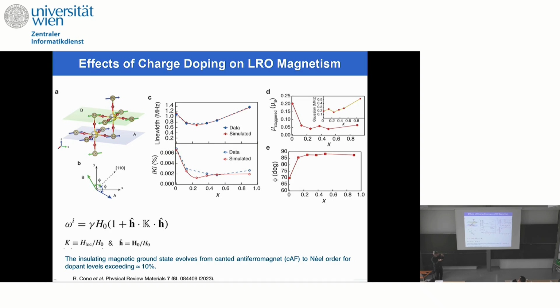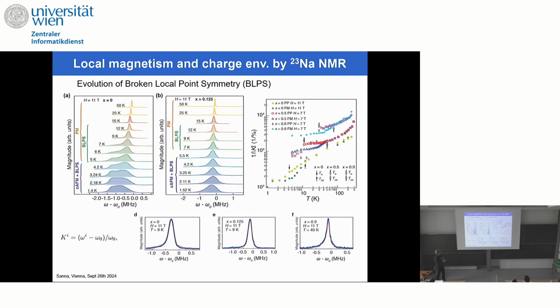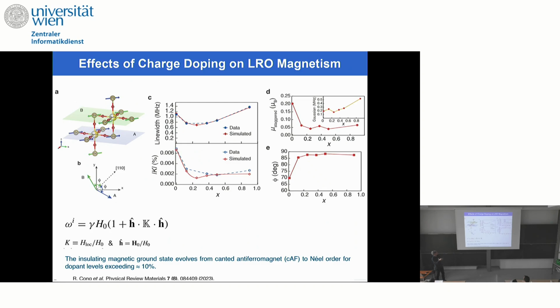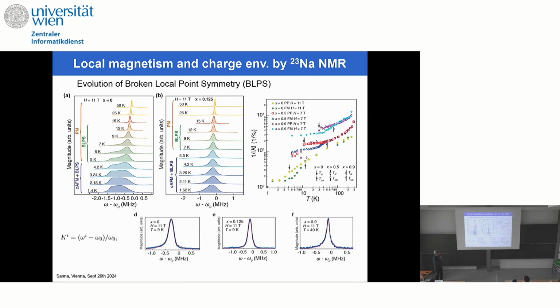and we can even detect the canting angle variation as a function of doping, which is canted here and almost antiferromagnetic soon after we dope the system with calcium. This is in agreement also with the magnetization measurements, the hysteresis magnetization versus field measurements. We are very happy about that. We can determine the hyperfine coupling and everything. And so we are happy that we can describe the magnetic behavior of the system as a function of doping.